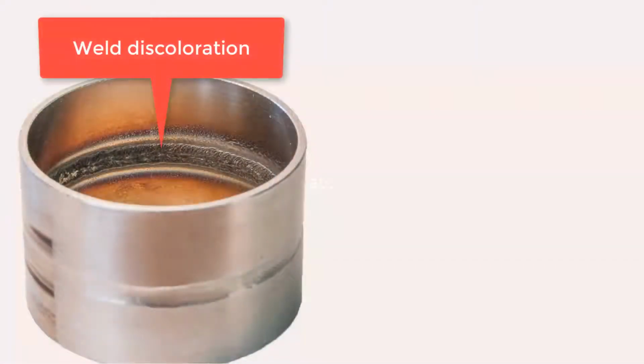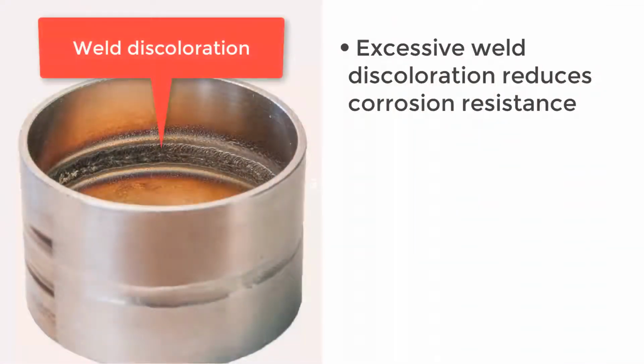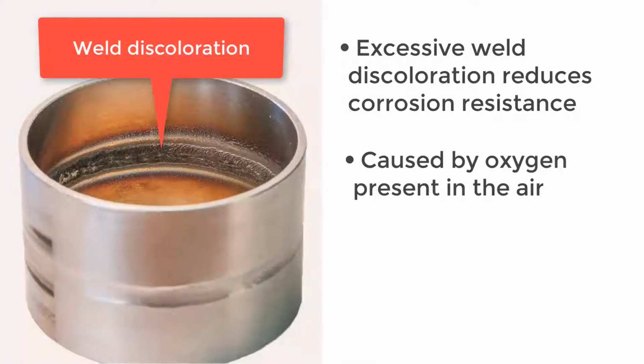Ensuring the purity of welding gases is paramount to producing stainless steel welds with optimal corrosion resistance by minimizing or eliminating weld discoloration. Excessive weld discoloration reduces resistance to localized corrosion in the heat-affected zone of a stainless steel weld. Oxygen present in air is the contaminating gas which causes weld discoloration. The nitrogen in air is inert and does not produce any discoloration.